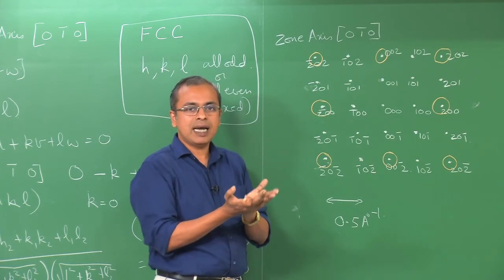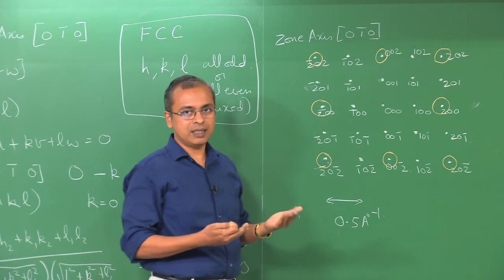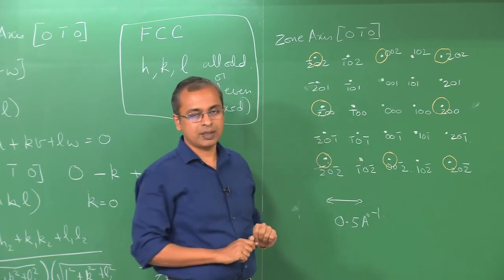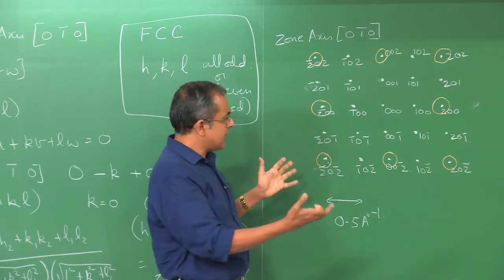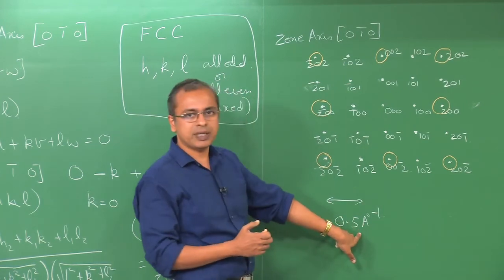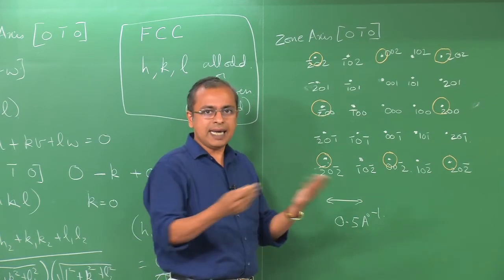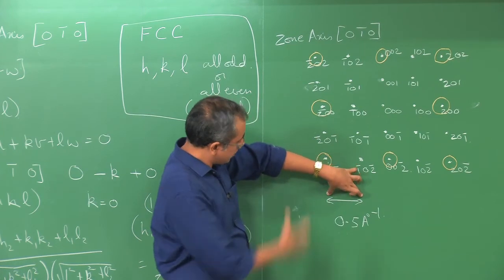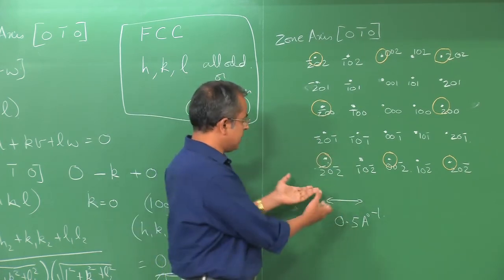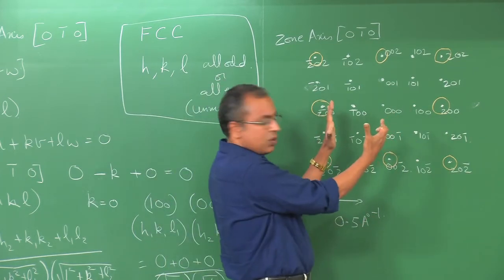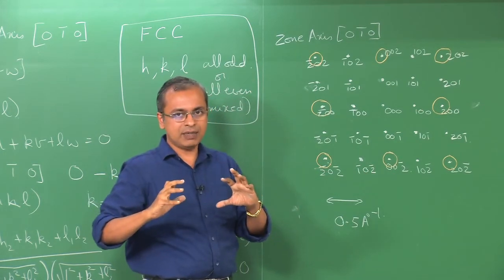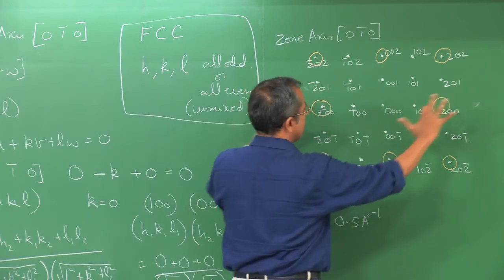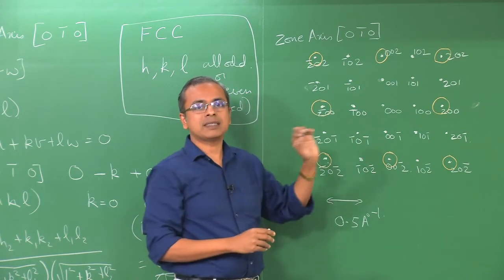This collection of points — this layout — is the diffraction pattern you will see when you perform electron diffraction of a face-centered cubic crystal with the beam aligned along the [0,1̄,0] direction. The reciprocal lattice points that you generate are directly related to the diffraction pattern that you observe. The only additional detail not addressed is scaling: the absolute spacing depends on camera length, but the angular layout of points is exactly the same regardless.